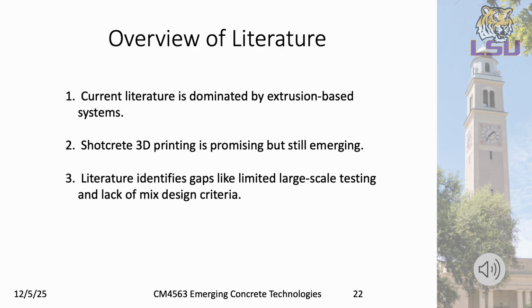More recent work exploring shotcrete 3D printing suggests that it could solve some of the limitations seen in extrusion, because the material is sprayed rather than extruded. Robotic shotcreting can create curved or free-form shapes and may even improve interlayer compaction and bonding. Researchers also emphasize how important the mix behavior is, especially the use of accelerators, fibers, and rheology control, to ensure the material can be pumped, sprayed, and still support new layers. At the same time, the literature makes it clear that the technology is still developing. There is limited full-scale structural testing and no established standards for mix design or performance yet, showing that while shotcrete 3D printing is promising, it still needs more research before widespread adoption.